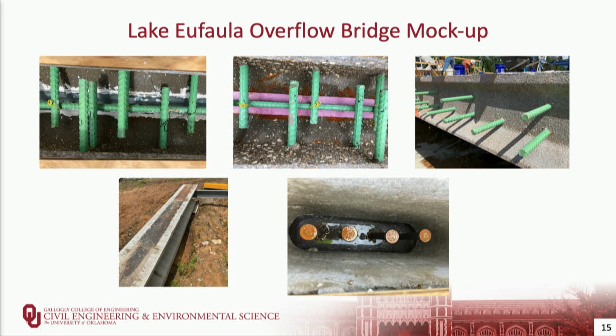They tested some different variables in the mock-up, which gave them an opportunity to see what would be the best construction method. Up on the top, left, and middle, they have a couple of different sealants that they used for the bottom of the joint. On the right side, you can see the exposed aggregate surface that was used for all the deck panels. And then these girders were actually pre-stressed concrete girders that had a steel plate embedded in the top to which the shear studs were welded.